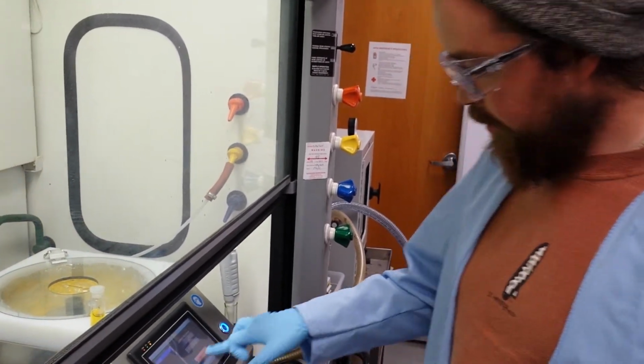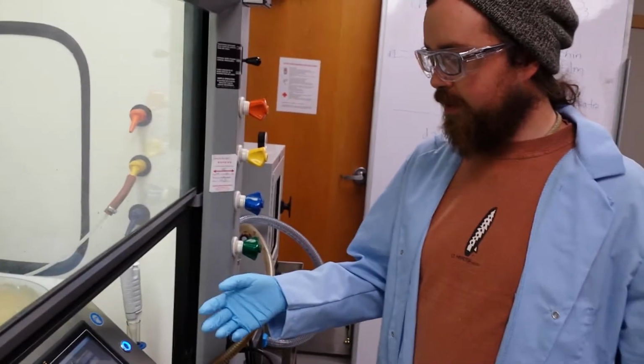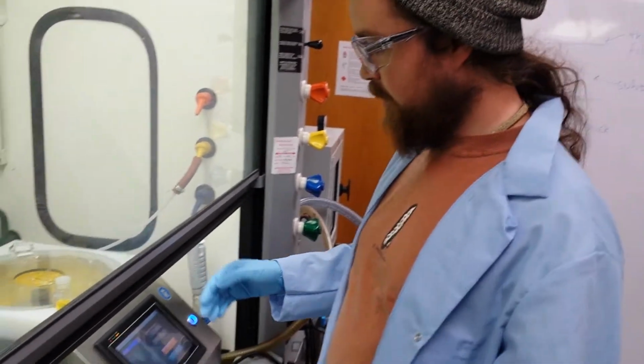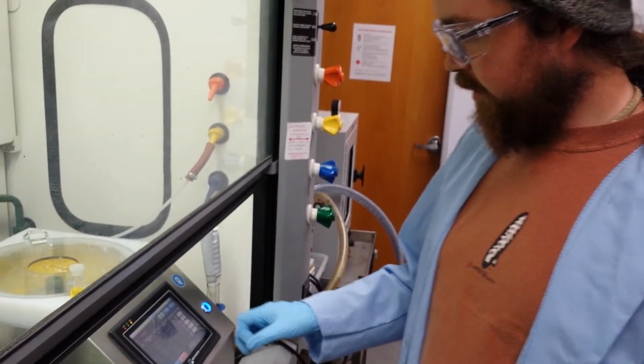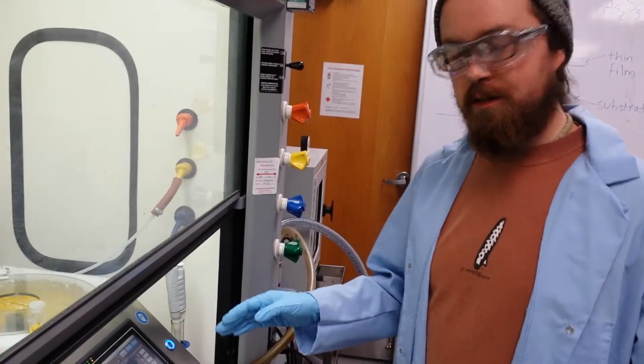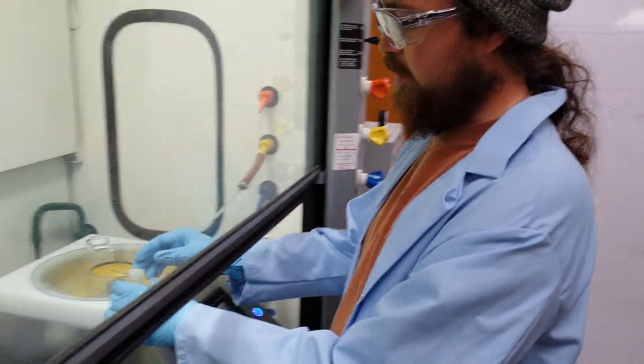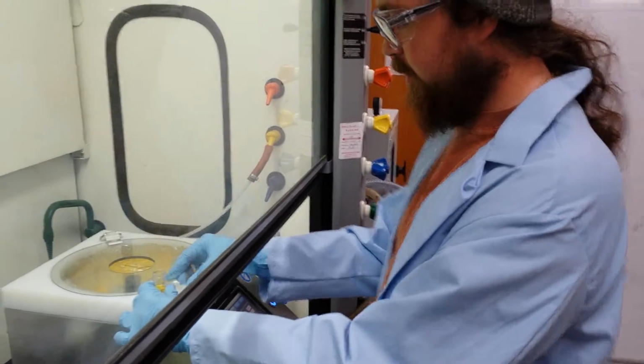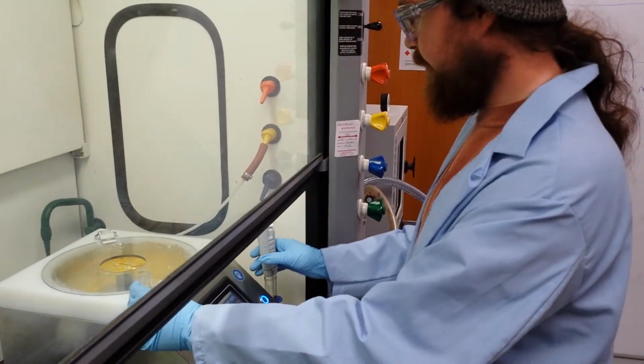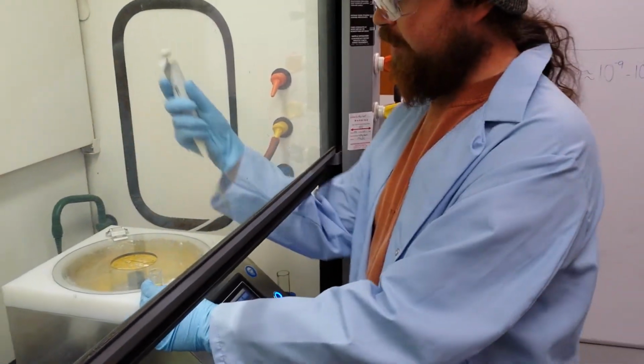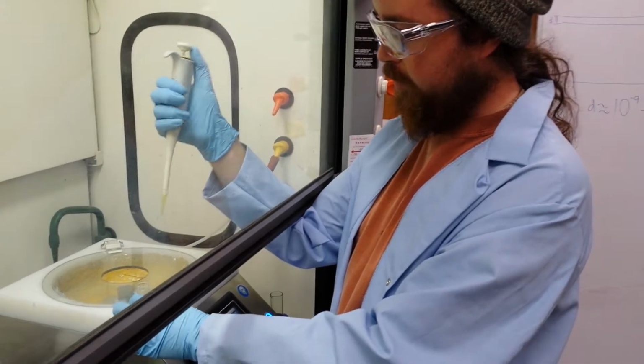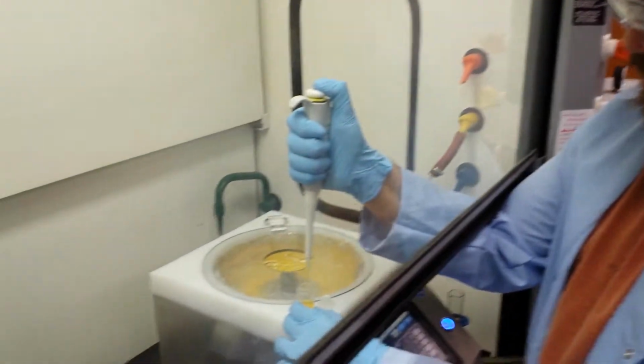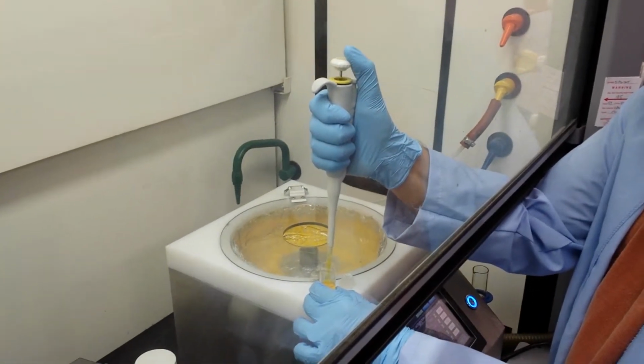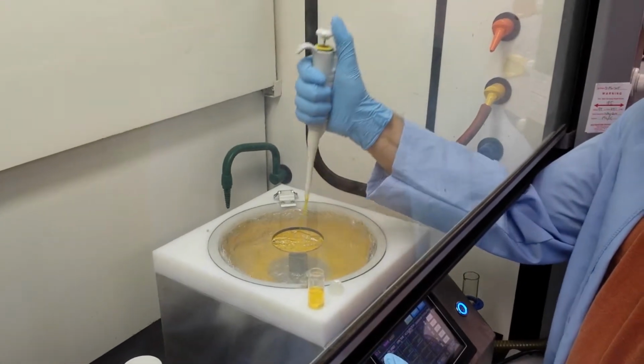And then what we're going to do is we're going to load up this program that I've made to actually deposit this film. So what the program does is it tells it to wait 7 seconds and then spin for 20 seconds. And these parameters have all been experimentally determined previously. So what we do is we take a pipette from any normal chemistry lab, and we get some of our solution into the pipette. And we're going to be pipetting 100 microliters onto this substrate.